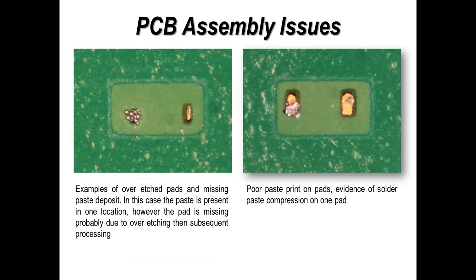Now, one of the other things we found in our study is that we could actually have boards with pads that were missing. And stepping back to probably 2008 or thereabouts, we also saw this problem with the initial trials on 0201. Remember, we're talking about very, very small pads, so the actual surface area of copper in contact with the laminate is relatively small, so mechanically they're not very robust.